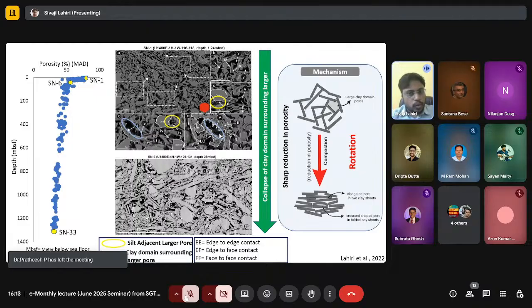Nevertheless, if we try to look at the particle contacts here in this sample, we dominantly observe 3 different types of particle contacts. That is edge to face, then edge to edge, as well as face to face. So all of these 3 types of particle contacts are very abundant within this particular sample.